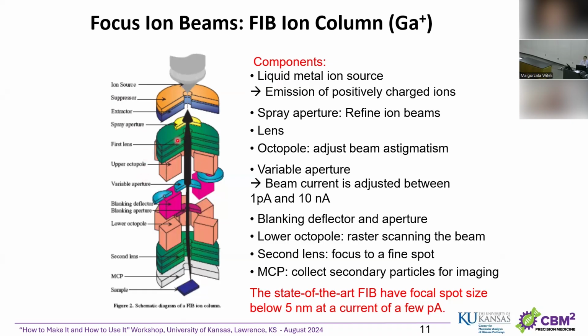This is not an optical lens, it's an electromagnetic lens. Simply speaking, because ions are positively charged, you apply a certain negative voltage so that you can either attract or repel those ions with this lens. The goal is to have a really focused ion beam. So here we have the first lens.